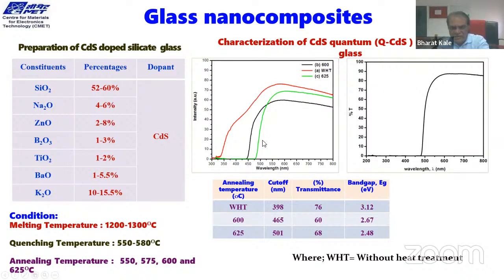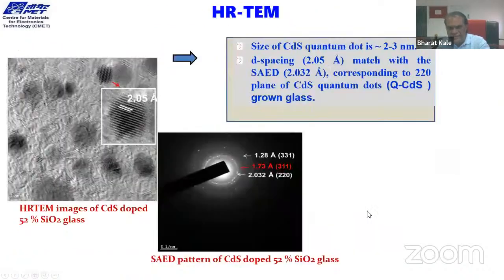When you grow cadmium sulfide embedded in the glass, the absorption is in the visible region, with the band gap coming close to 2.48 electron volt, which is that of the CdS band. This is very unique, so in situ growth of CdS is very important. We can tune the band gap from 3.12 electron volt to 2.48 electron volt by growing the CdS size here. See an isolated particle here, one quantum dot of 2.5 nanometer. If you see the SAED pattern, you can observe a very bright ring, which indicates that though the size of the quantum dots is very small, they are highly crystalline. That is very important in our case.